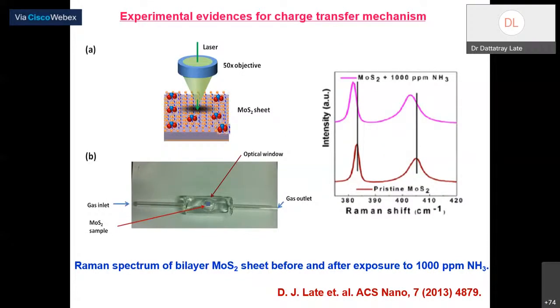I have also done an experiment to find out the exact origin of this gas sensing mechanism, and we find that charge transfer is the origin. How did we do this experiment? We put the single layer MoS2 device in a glass container, with one optical window, a gas inlet and a gas outlet. First we did a run with nitrogen or argon gas and recorded the Raman spectra. We find that the difference between these two peaks is almost 18 cm⁻¹, which is characteristic of single layer MoS2.